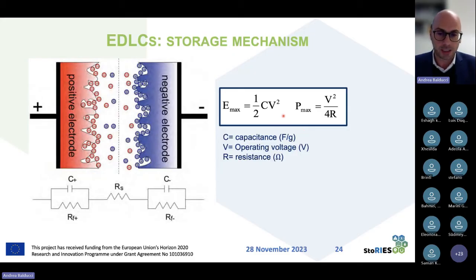Why? Because we see that the maximum energy of these devices can be described by this simple equation. It is equal to half of the capacitance, which is basically farad per gram, so the capacitance of the electrode, times the square of the operative voltage. And the power is given by the square of the operative voltage divided by the resistance of the system. This makes it immediately clear that in these devices, if we want to increase the energy, as we discussed before, we need to increase the capacitance, and we need to try to increase as much as possible the operative voltage, because of course, every increase of operative voltage will have a strong impact on the energy because it goes with the square of this parameter.